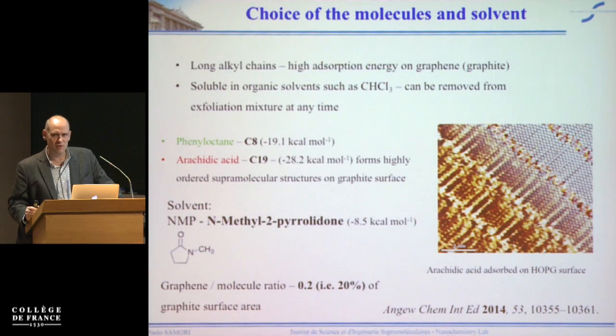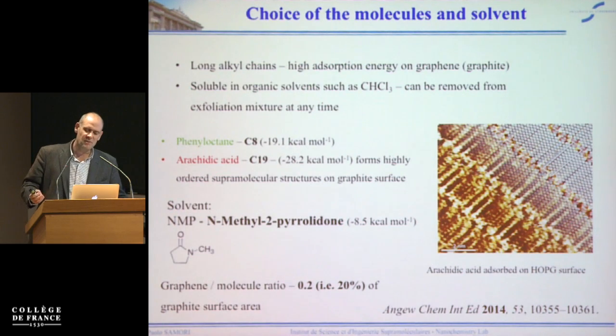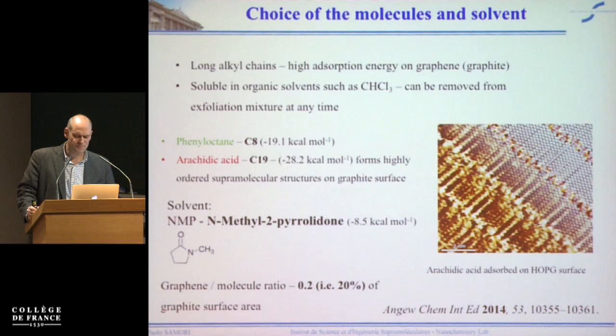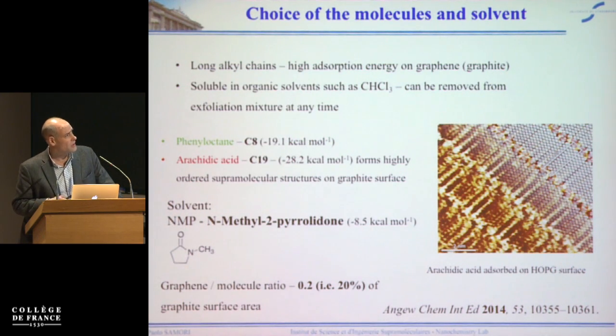This is interesting for us because one of the applications we have in mind is electronics. And actually, we found that from the solvent mixture, we can separate the alkanes from the graphene just by exposing this to 70 degrees, okay? And so we take advantage of the alkanes in order to promote the exfoliation, but then we get rid of them. You can use different types of alkanes.